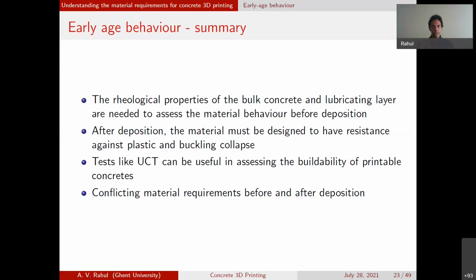And even when we analyze it as a Bingham fluid, we see a huge discrepancy between the predicted and experimentally observed value. This is because we don't account for lubricating layer properties. If you do account for lubricating layer properties, better estimates can be made. And from these estimates, the type of pumping system required for use in 3D printing can be designed. Once it's deposited from the nozzle, we need to understand how failure can happen.